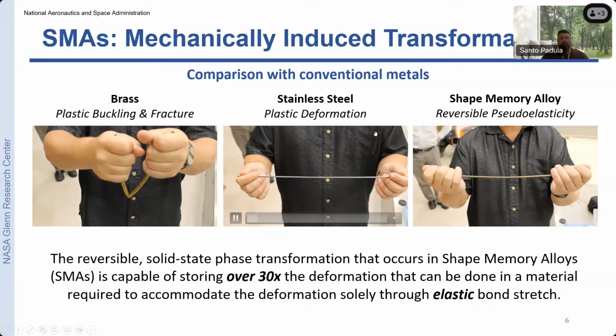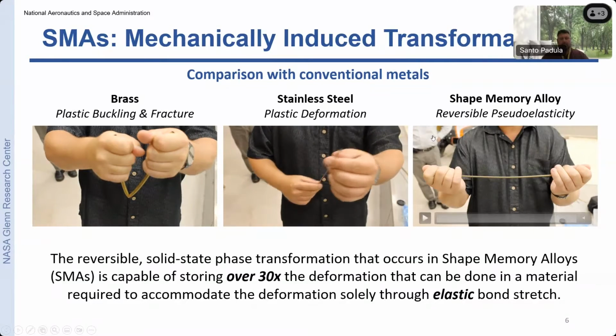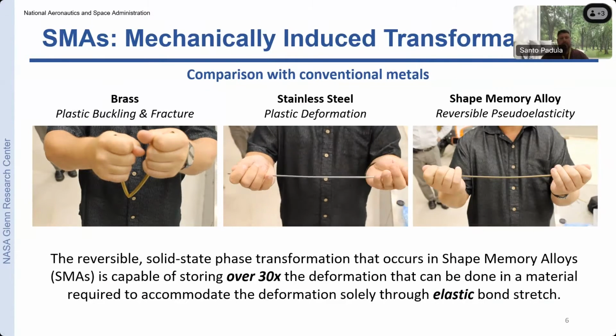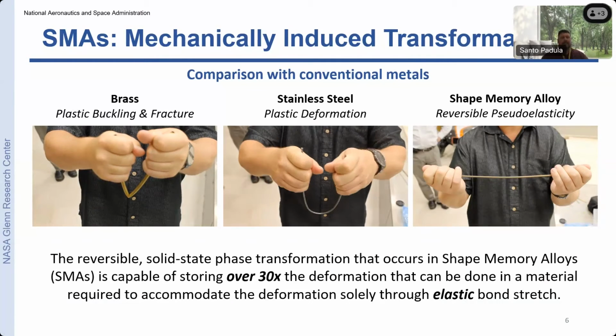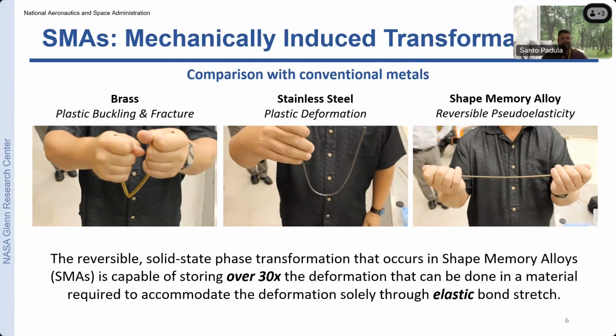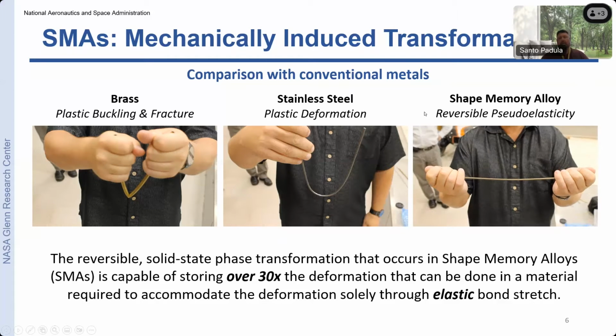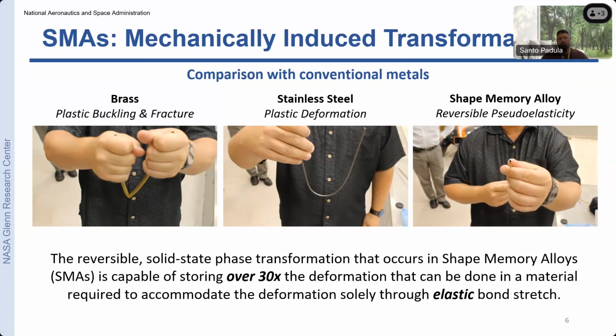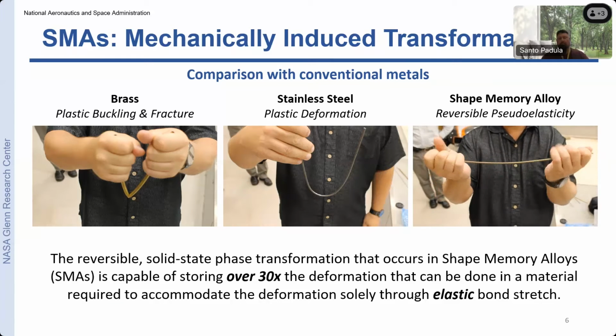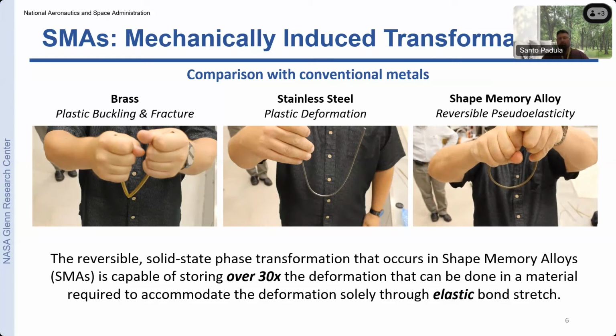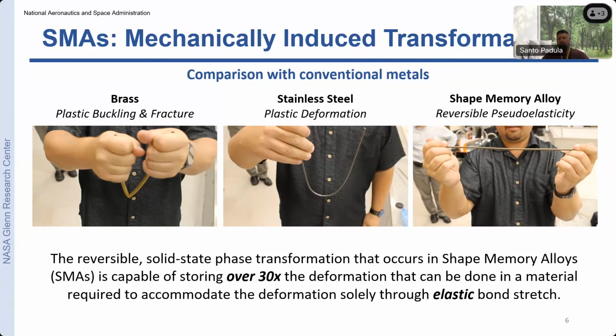In the case of stainless steel, we can take a similar tube, and if we apply those deformations, we get a little bit of elastic distortion before we begin to severely plasticize the system. And of course, in those two systems, none of that is recoverable. We've gone far beyond the reversible potential of those systems. However, in a shape memory alloy, because of this reversible solid state phase transformation that's available, we can put the same deformations in the tube and revert the entire structure back to shape.